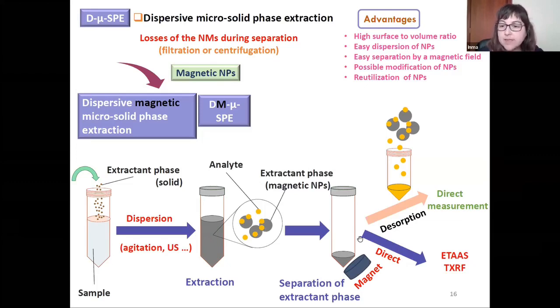If we make the direct analysis, we can do this analysis with ETAAS or TXRF, which are suitable for a suspension or a slurry sampling. However, for other techniques like ICP-MS or ICP-OES, we need to do a desorption or a dilution of the analyte, for example, with diluted nitric acid, which is the typical eluent used. And then we analyze the eluent by these techniques because they don't allow the use of particles.